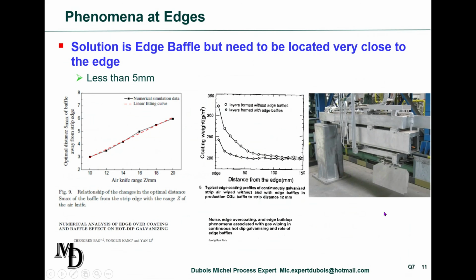So how can you solve that, for example? It is the baffle. And I especially like two excellent papers where you can find a reference here at the bottom. It is not new. Those ones are Korean authors who investigated in the lab the coating weight variation versus the nozzle to strip distance. And without an edge baffle, the coating thickness on the extreme edge can be as high as 50% more. And I verified that myself also online. And as soon as the baffle, that's only a simple plate, is there, just to avoid that the two nozzles face each other, it decreases significantly.